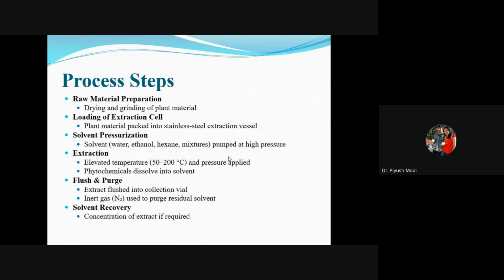In this method too, the steps are first drying and grinding, for size reduction of the plant material, then loading it into the vessel. We most probably use stainless steel, because certain oils are acidic. Like I said about rosemary oil, some acid, rosmarinic acid, is available in its composition. So most essential oils are processed in an SS vessel only.